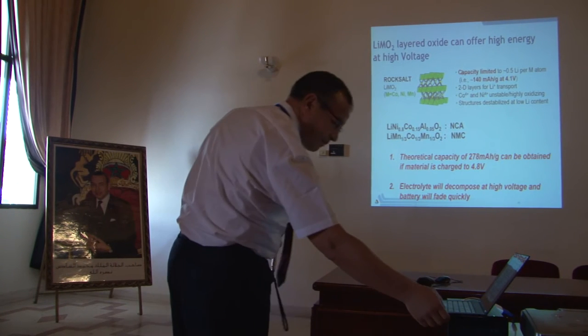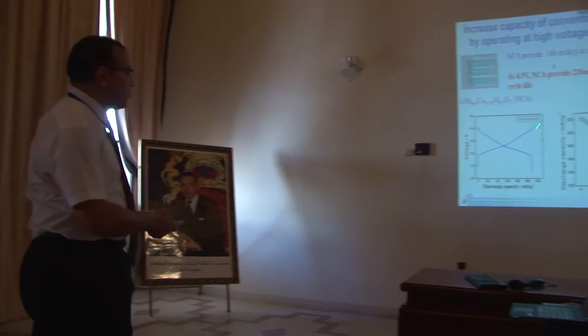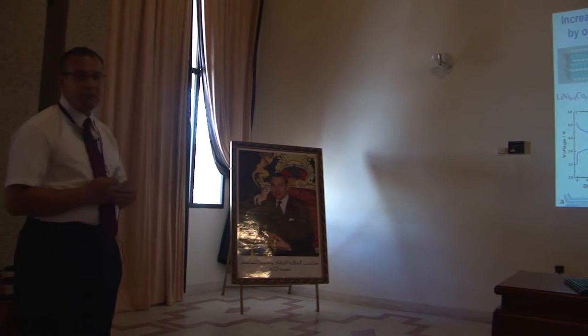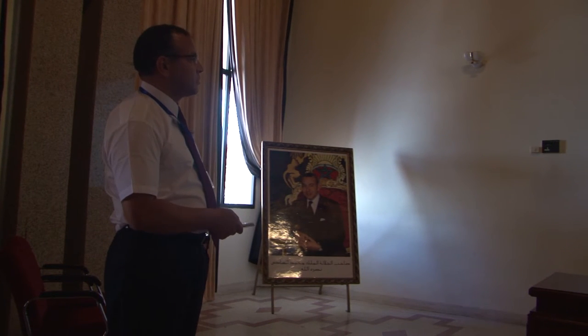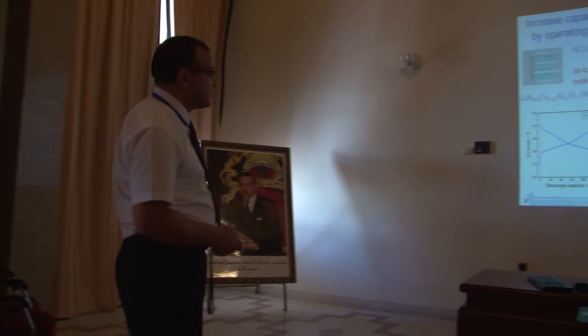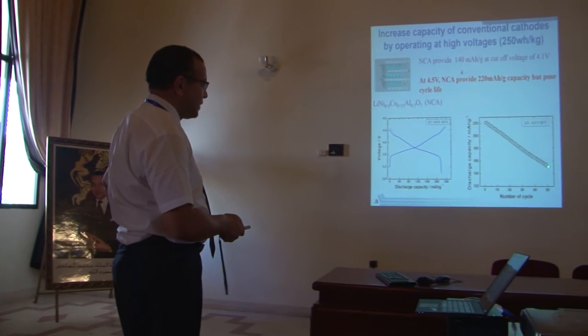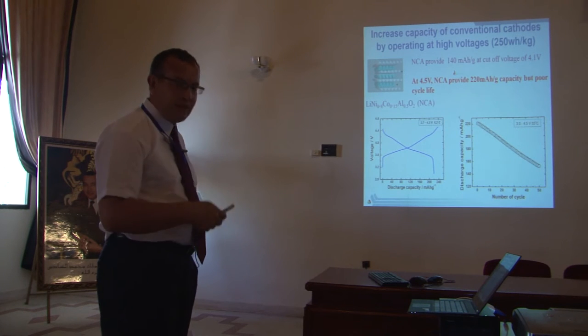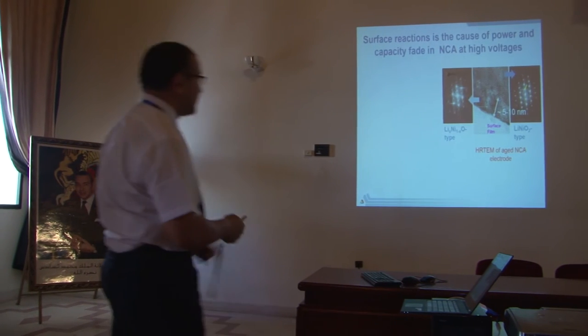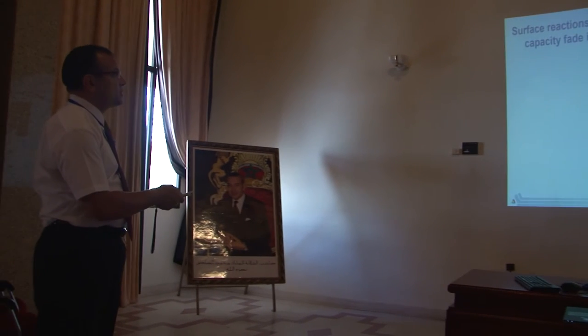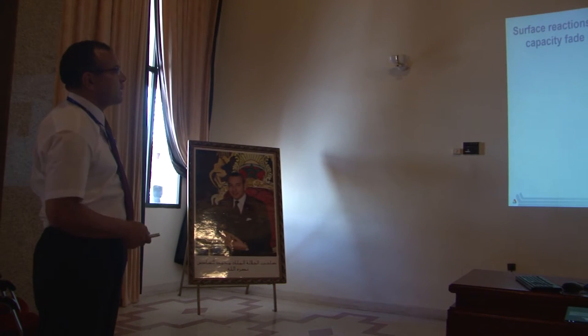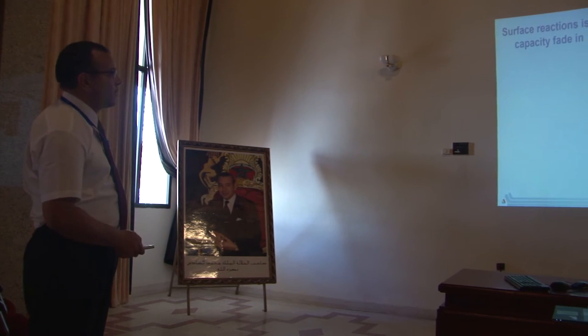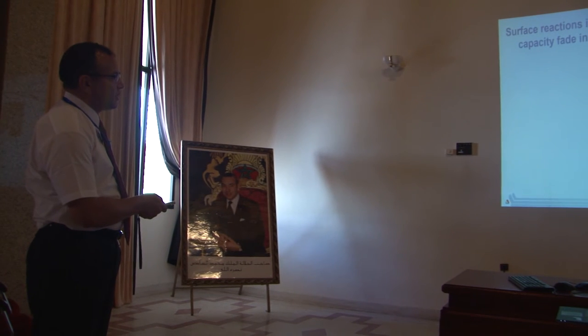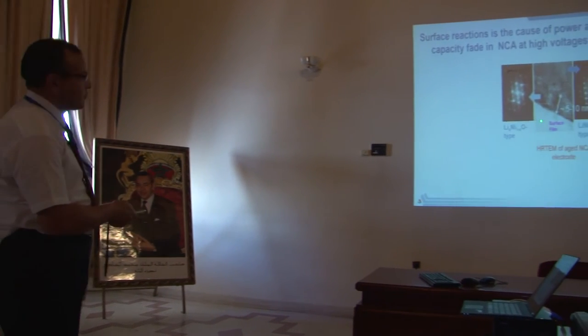And here is an example. For example, you go to 4.5 volts, you can achieve almost 230 milliampere hours per gram with the existing technology, which is the NCA. But if you cycle it, you can see it goes down very quickly. The reason why it goes down so quickly: if we take one particle here and microtome it in half after cycling, this is what you get. This is a high-resolution transmission electron microscopy image. You can see the layers of the NCA structure. And then, you see from the electron diffraction, it is a layer type. You have another phase that is formed, which is a nickel oxide base, and you have a surface film.